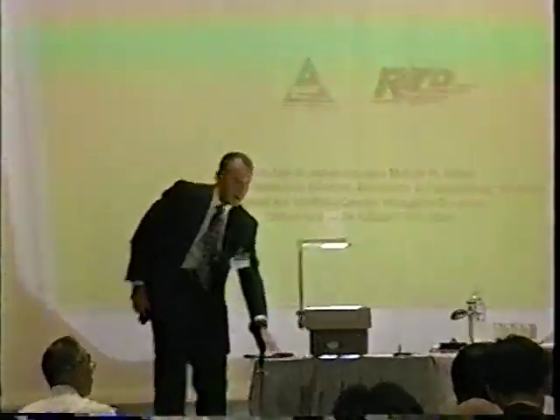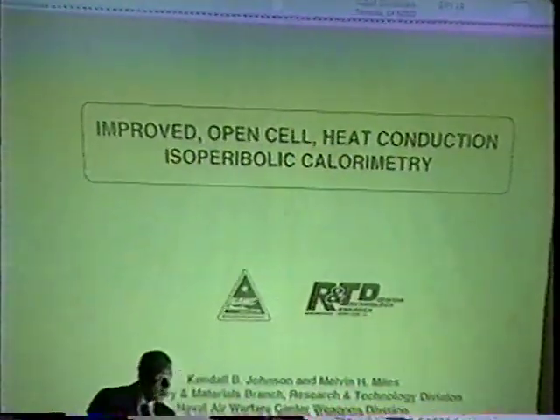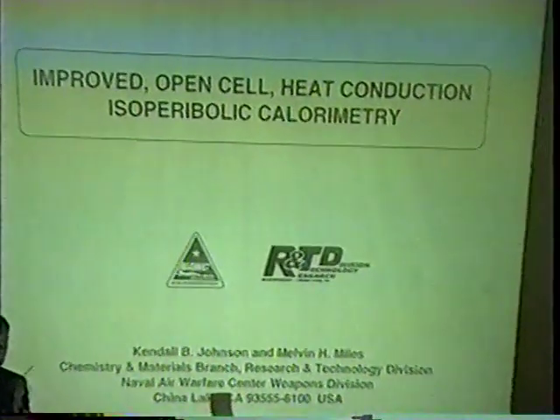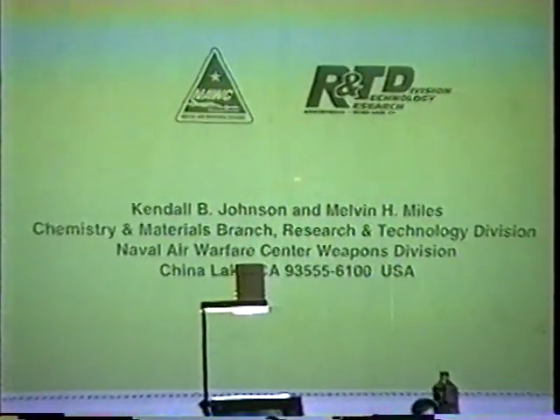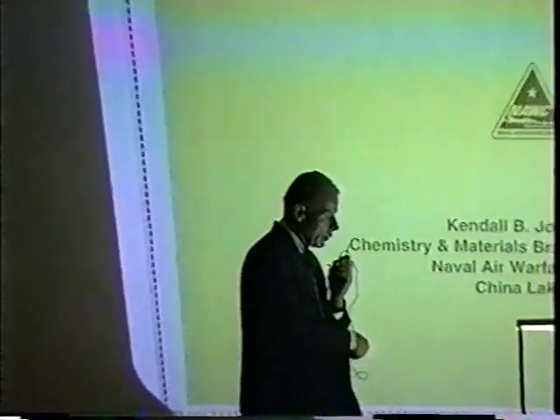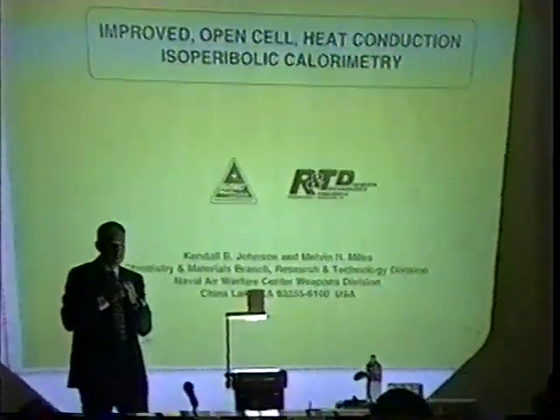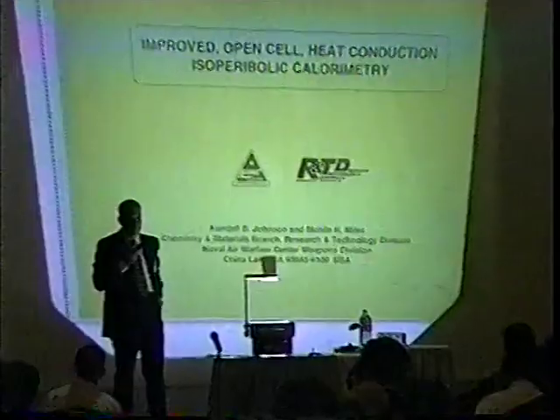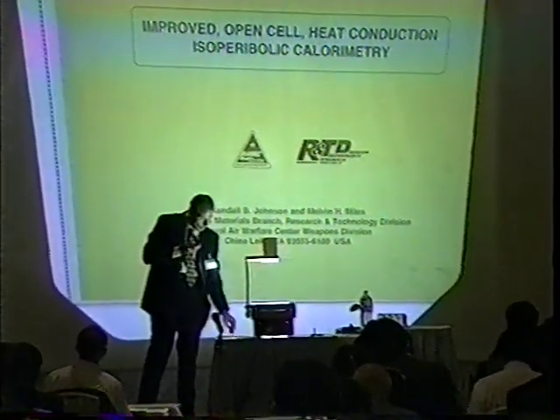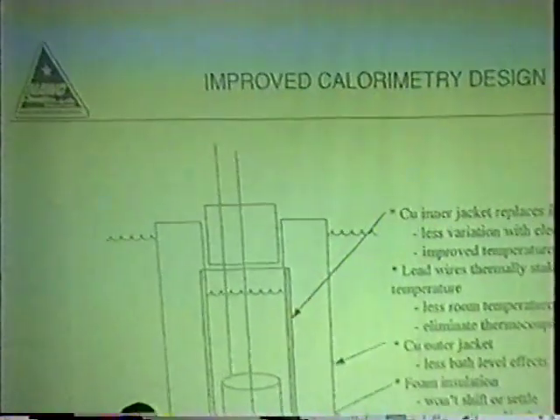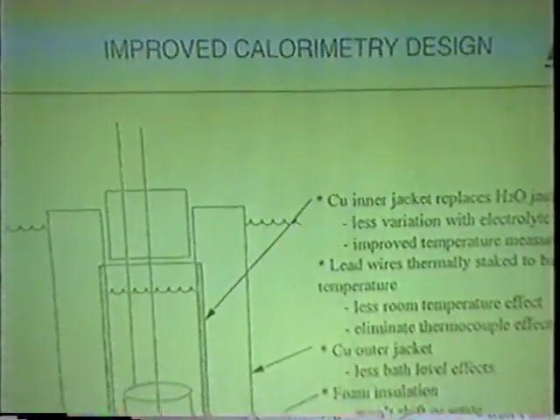Improved open cell heat conduction isoperibolic calorimetry from Dr. Miles. This calorimetry is an improvement over what we had been using, what we reported on this morning. Kendall Johnson was a postdoc. He was the one that did a lot of this designing. And the purpose was to measure more accurately excess heat effects in things such as deuterium absorption into the plate. I won't go over this, but at the poster you can go over the things that we did to improve it.